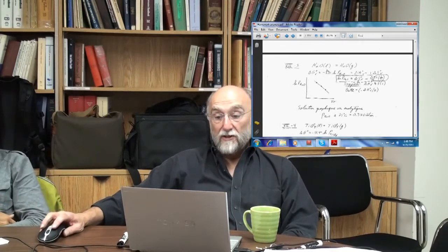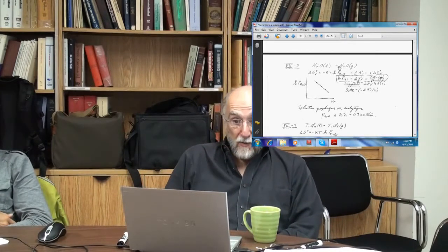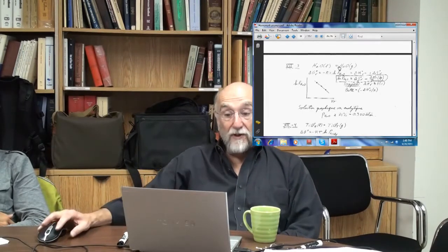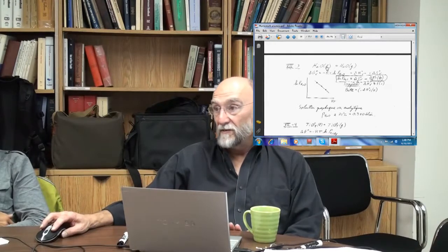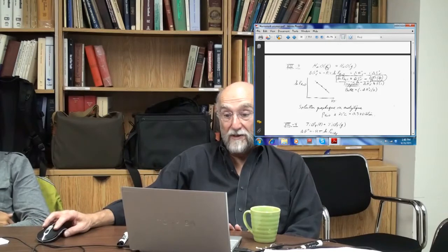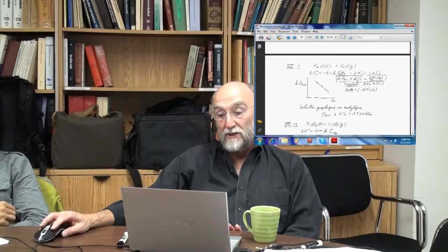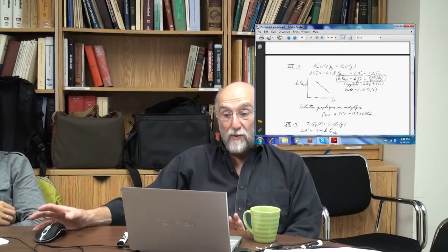So this is your equation. This is your equilibrium. You have an equilibrium between liquid water and gaseous water. And the delta G of any reaction is minus RT log K. K for the reaction is the equilibrium vapor pressure divided by the activity of the liquid, just like any chemical reaction. There's no difference here. Delta G0 is minus RT log of the equilibrium constant, which is the partial pressure of the gas divided by the activity of the liquid. The activity of the liquid is 1 because it's pure water.